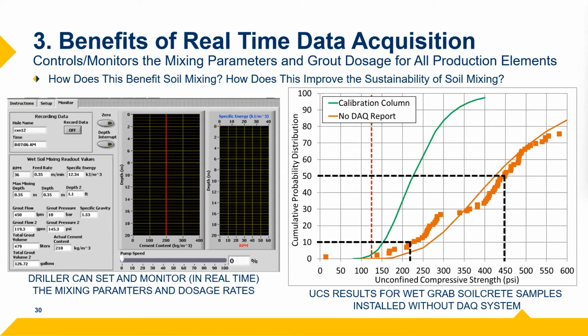We can start adjusting our grout design accordingly based on this quality data. The one thing I want to point out though is our average is about 450, and we have break values that are at about 600 PSI or higher. So you see a huge variation in what we're getting from our quality program, right? We're going out, we're grabbing these wet grab samples, we're curing them, we're waiting 28 days to break them. And we're seeing anywhere from about 120, 130 all the way up to 600 plus PSI. So it's kind of a huge variation.